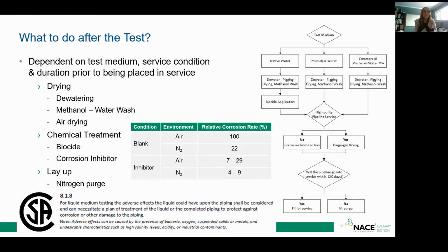However, if you're to use an inhibitor, you can really drive that corrosion rate down, even if you're not using nitrogen. So just because the pipeline isn't going into service right away doesn't mean that we shouldn't be applying corrosion inhibitor after the hydro test to really remove any impacts of having that hydro test water setting up corrosion cells in your pipeline. And so I highly recommend that the folks in projects communicate with their integrity specialists to ensure that they're appropriately addressing the corrosion that could happen in their line, and integrity specialists working with your chemical vendors to find the right solution for your pipelines and your service.